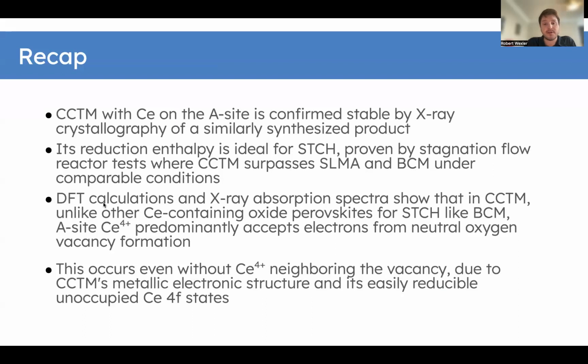DFT calculations also showed, as well as X-ray absorption spectra, that unlike other cerium-containing perovskites for STCH, like BCM, cerium is on the A site and in a high oxidation state, and despite that being the A site, which tends to be a more chemically unreactive site, it accepts electrons even when it doesn't neighbor vacancies that form. This is really some interesting physics going on, and I think it warrants a lot more characterization in the future. But right now, our main goal is getting this material on sun.